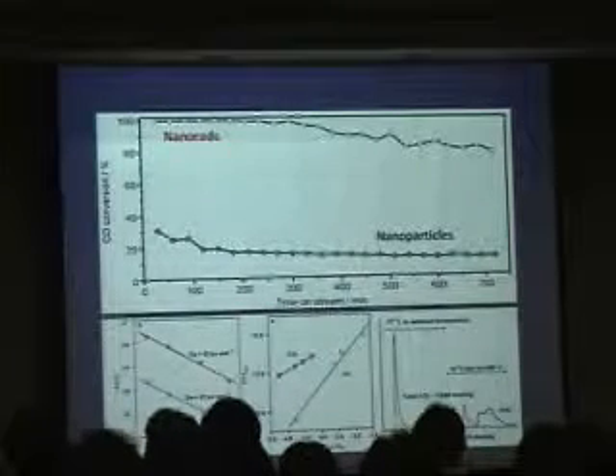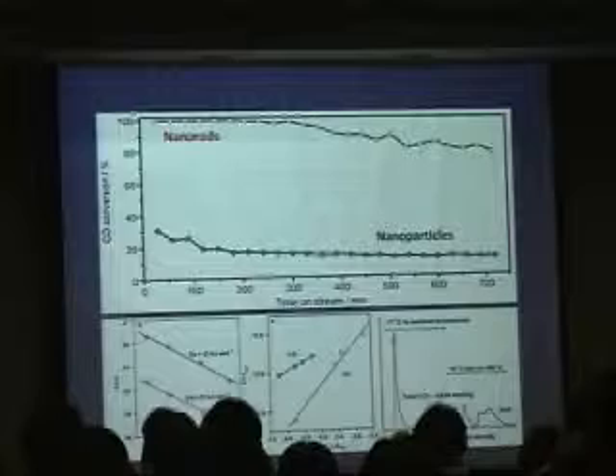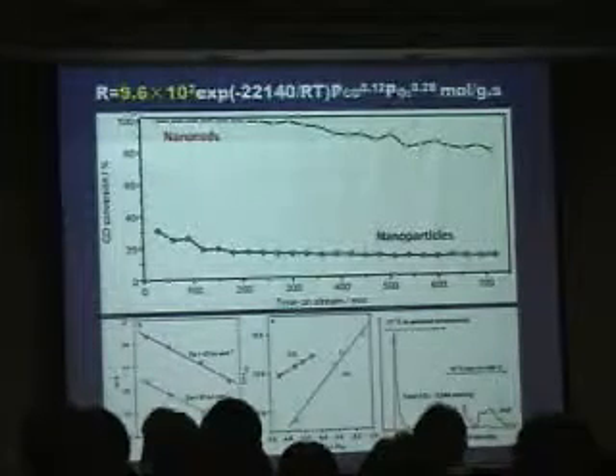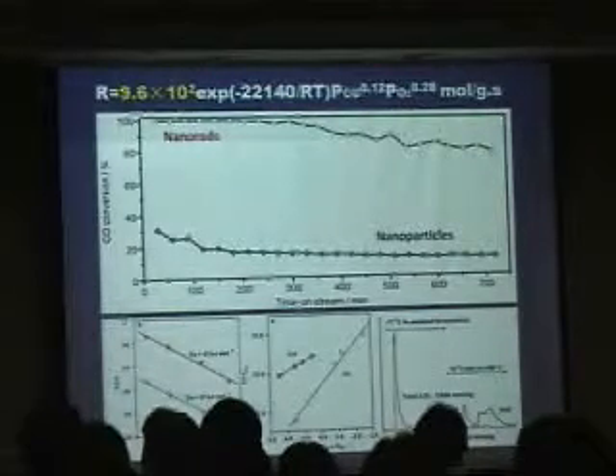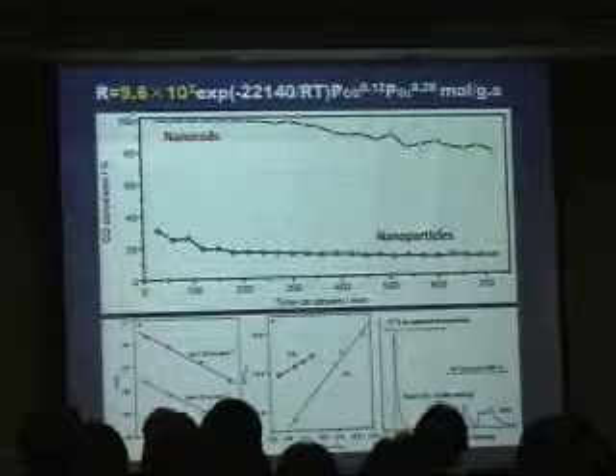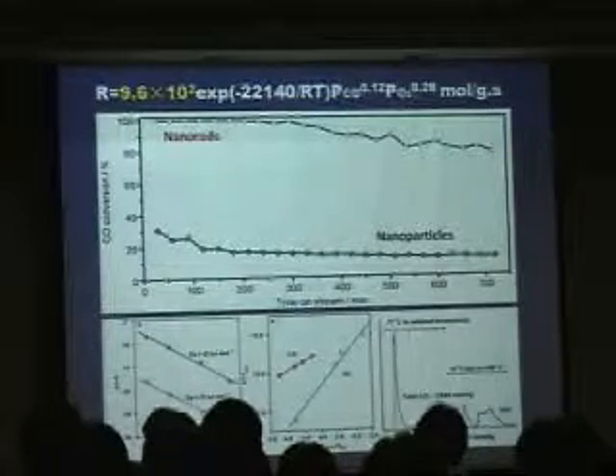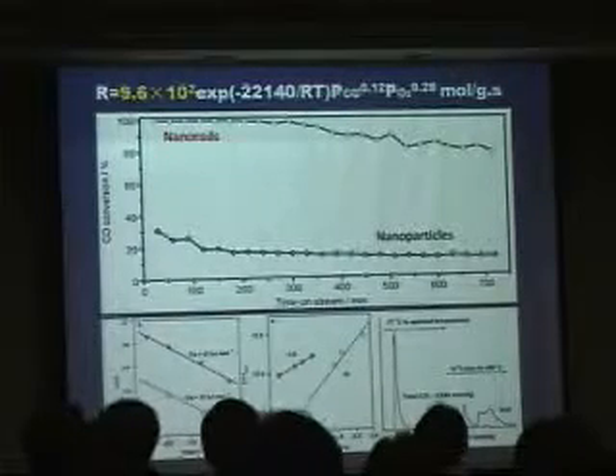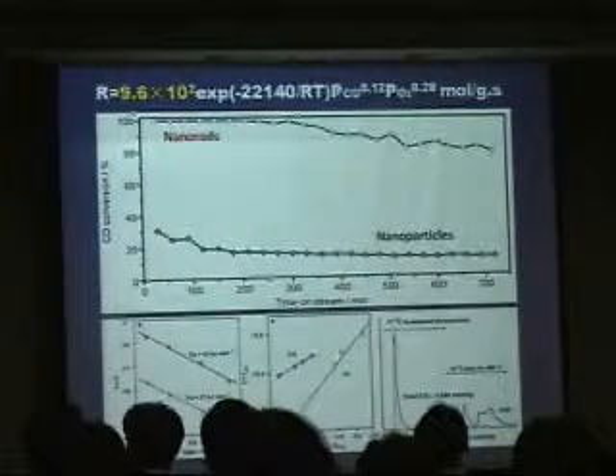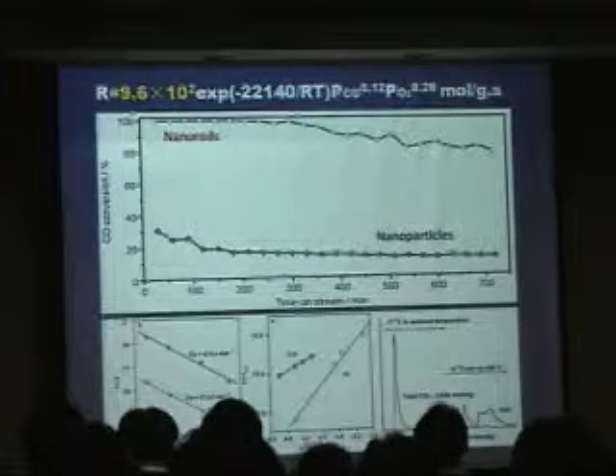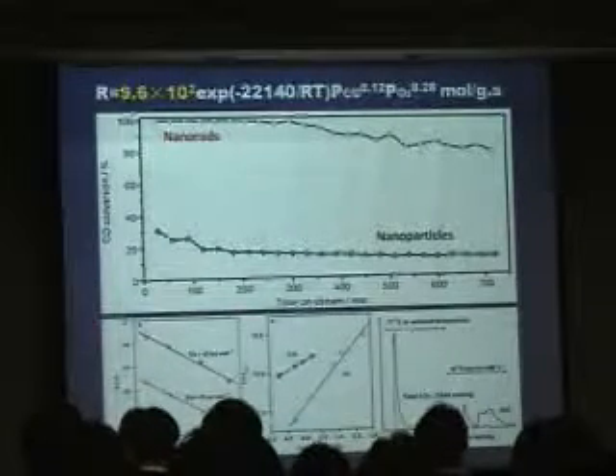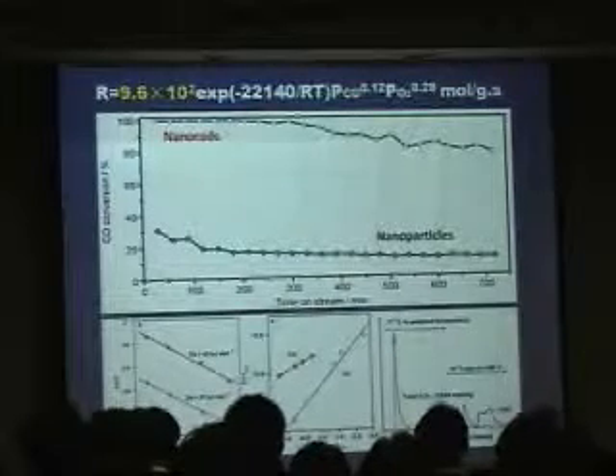And we analyzed the kinetics for these particles. We find that the reaction kinetics is the same. Activation energy and also reaction order with respect to CO and oxygen are almost the same. The only difference is the reaction rate, this parameter increases very much. That means the number of the active sites in the nanorod shape is about 10 times larger than in the nanoparticles. If we perform some chemical titration analysis, we can confirm this.